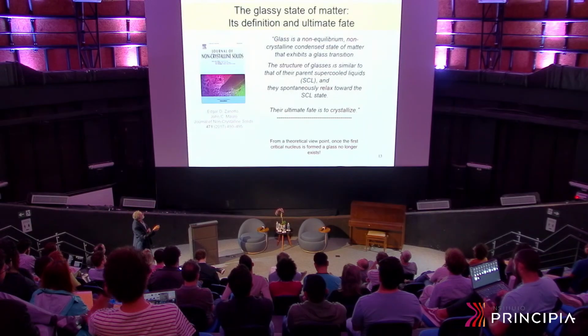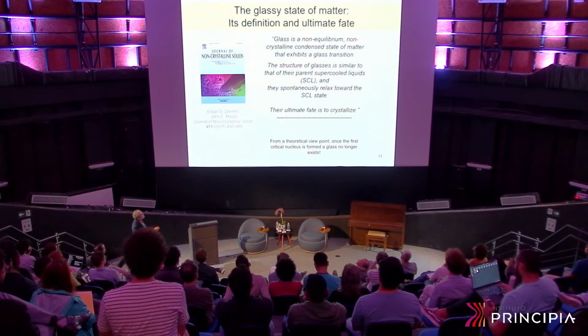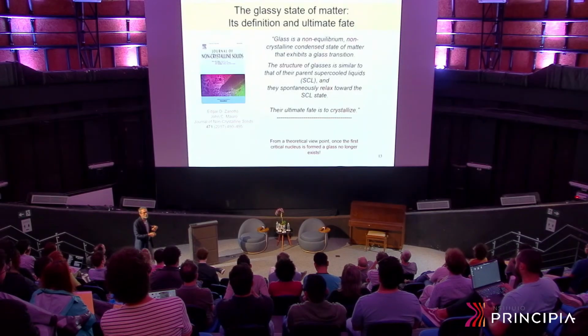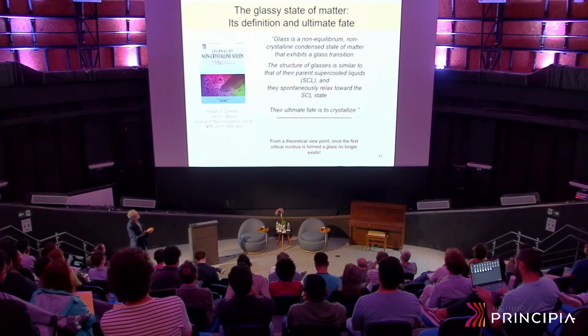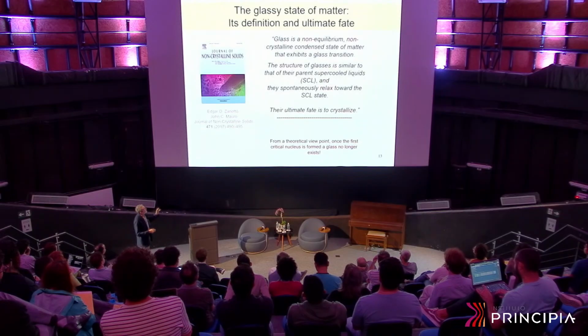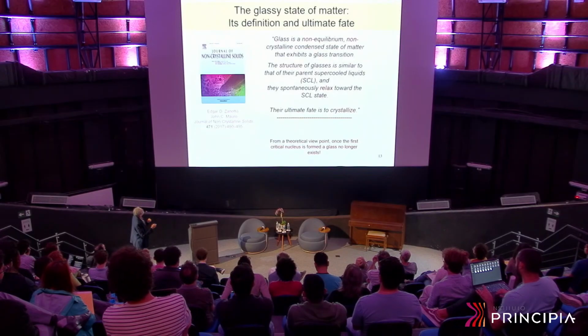The structure of glasses is very, very similar to the structure of their isochemical liquids. Same structure. They all spontaneously relax to the supercooled liquid state. That's why they're unstable materials. And the ultimate fate is to crystallize. This is my favorite definition, although not all authors agree with it. There are other definitions in the literature.